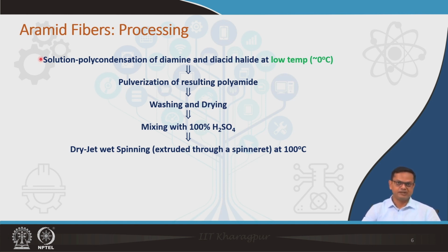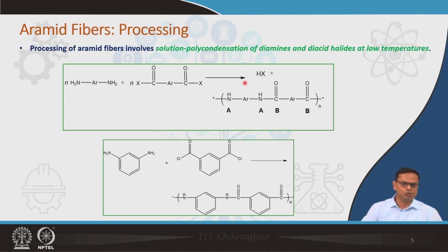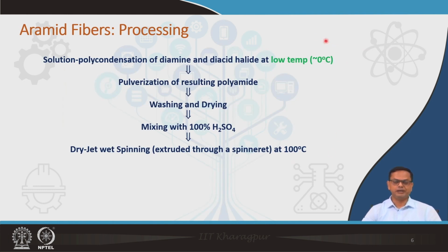So, the first step is that you go for solution polycondensation of diamine and diacid halide. Let me just go back once more. This is the diamine and this is the diacid halide. These two molecular structures go through solution polycondensation, and that gives this particular aramide structure, and the reaction takes place at a very low temperature, in the range of 0 degree Celsius. And that leads to the formation of the aramide.